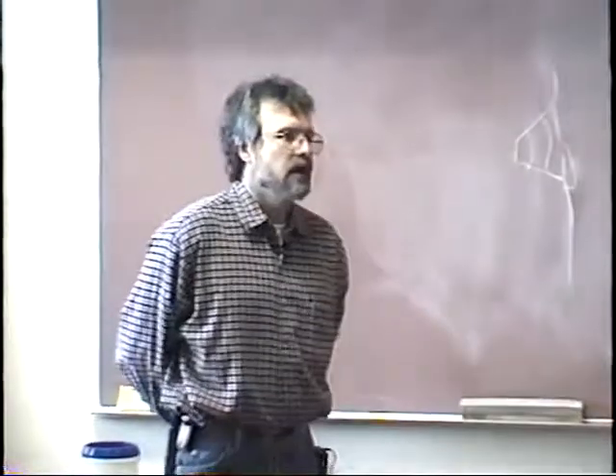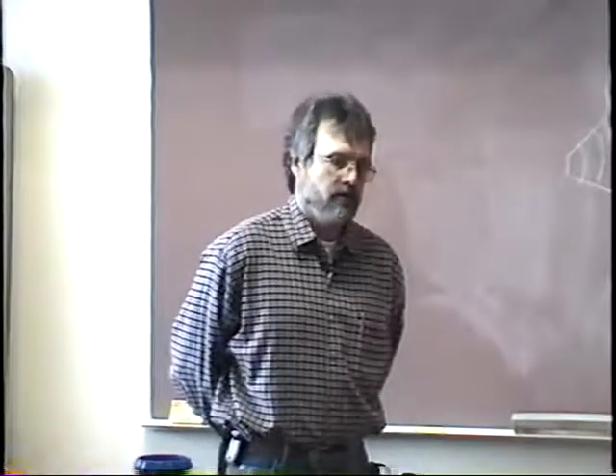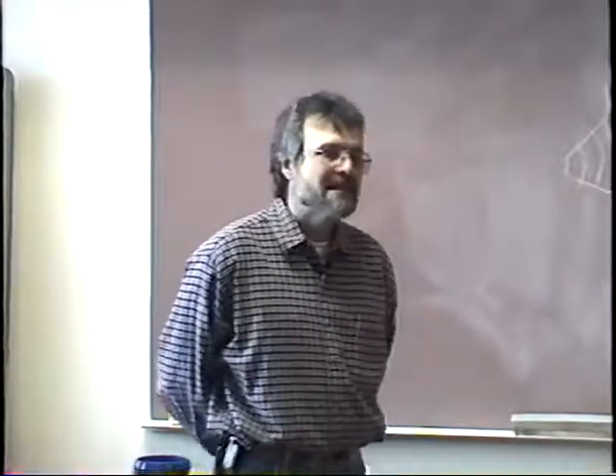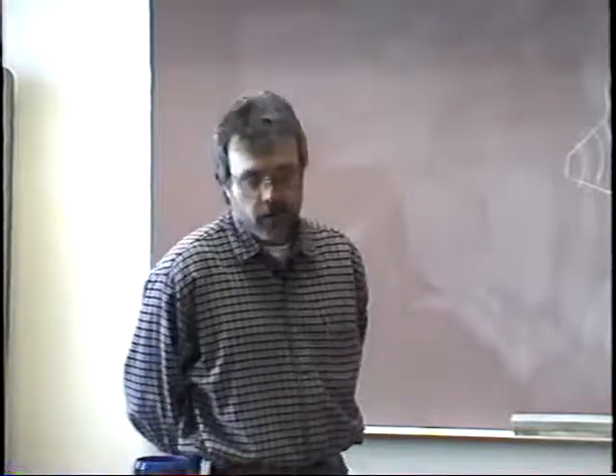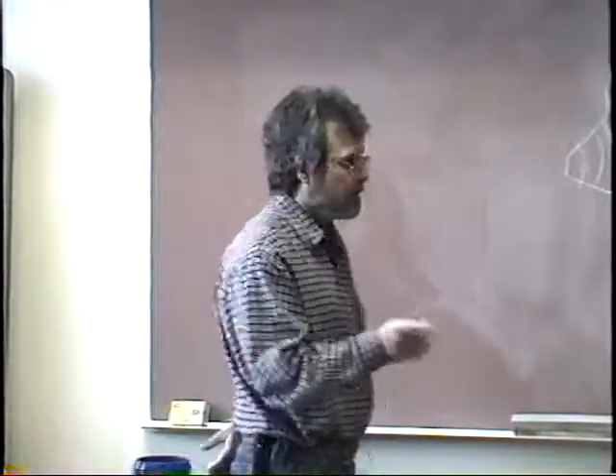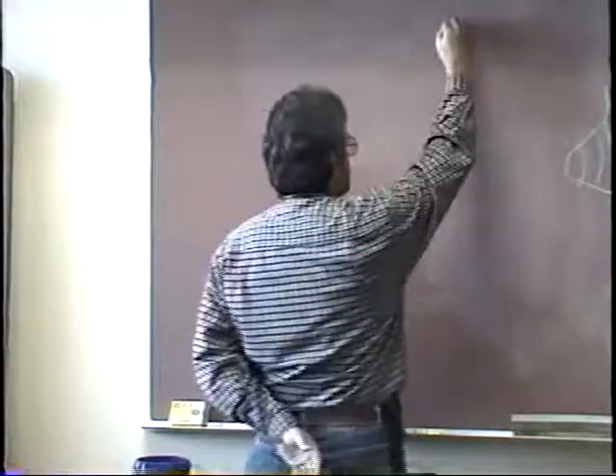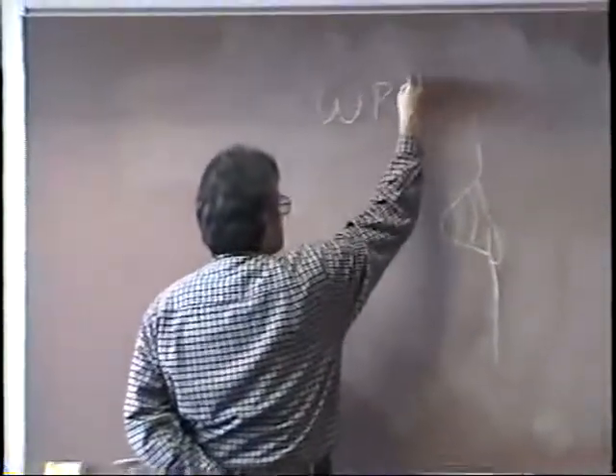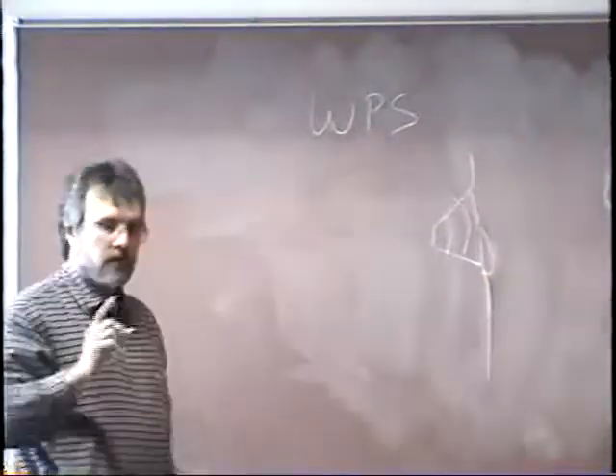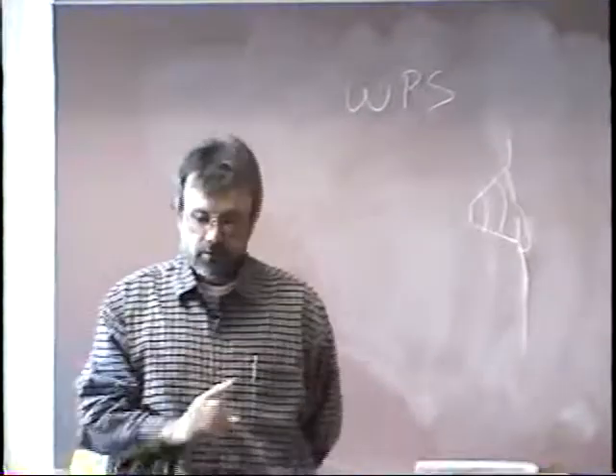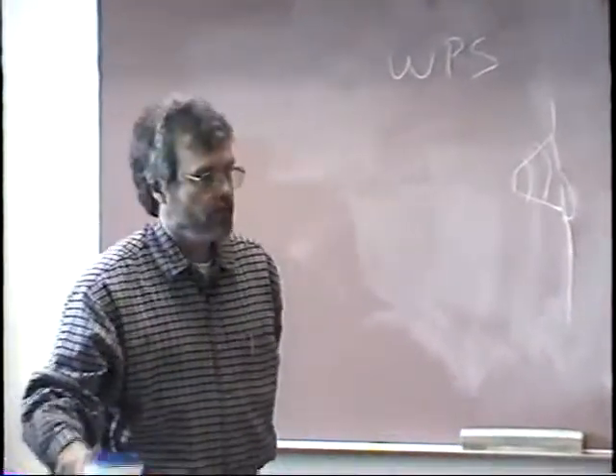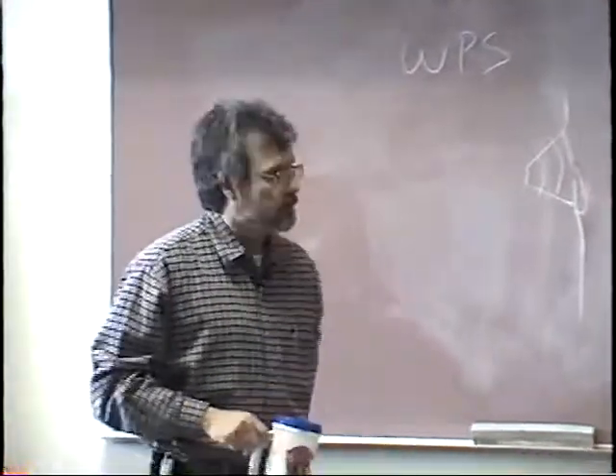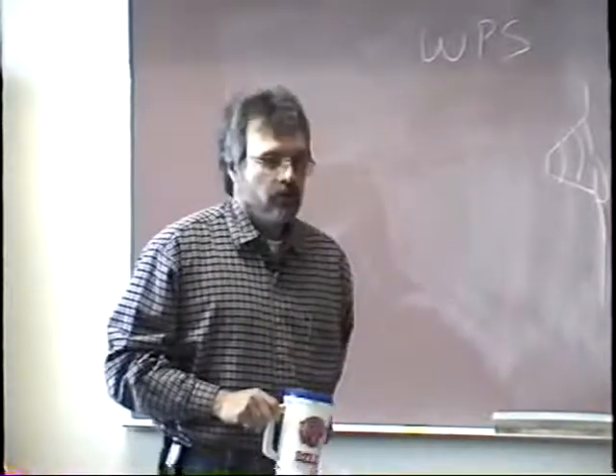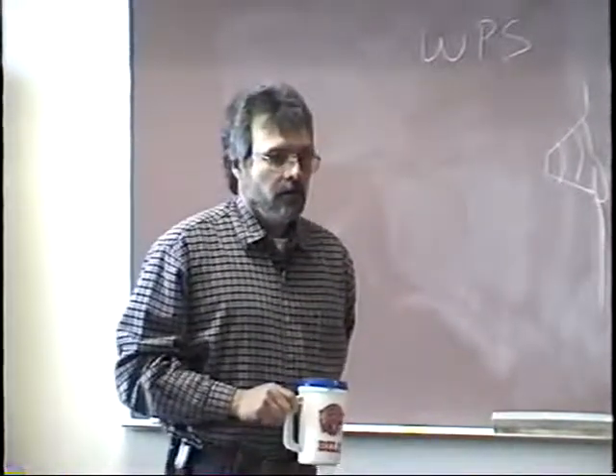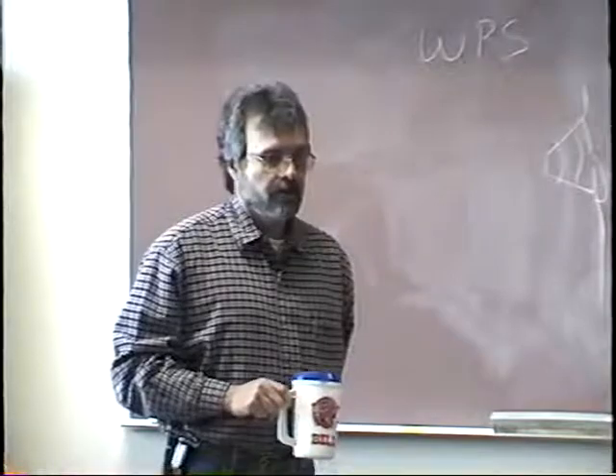Basically, if you're using a high carbon steel or an alloy steel that has a propensity for cracking, you've got to preheat it. And again, if that's the case, read your WPS. Your WPS will tell you if you're supposed to preheat it, and make sure you do preheat it. If the welding inspector comes by and sees you welding on something and there's not a torch within 50 feet of you, you're going to get your ass reamed out for that.